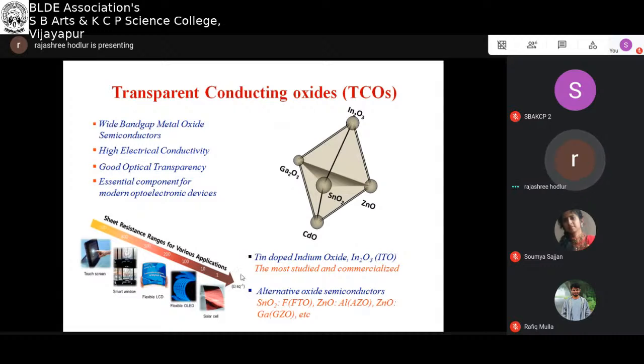So this figure shows how the conductivity, say the sheet resistance, so 500 ohms per square, is used in touchscreen. The transparent conducting oxide with a sheet resistance of nearly 400 ohm per square is used in smart windows. Similarly, if you see the solar cell, the sheet resistance is around 1 ohm per square. Okay, so depending upon our interest and requirement, we can tune the sheet resistance or the electrical conductivity of these transparent conducting oxides. So here are some examples of metal oxide semiconductors.